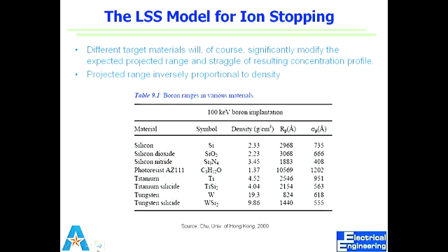So to make that 30 nanometer depth, if I want to use silicon dioxide, then this plot will tell me how thick silicon dioxide should be to be used as a reliable mask. It can be used as a mask even if you use 20 nanometer, but a reliable mask is one where no ion passes through, or negligible ions pass. Does that make sense, guys?